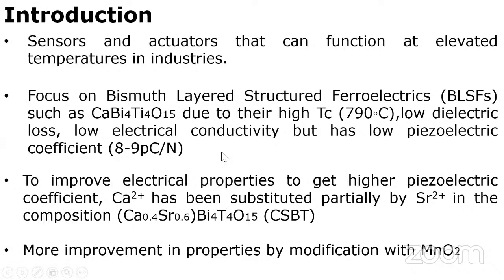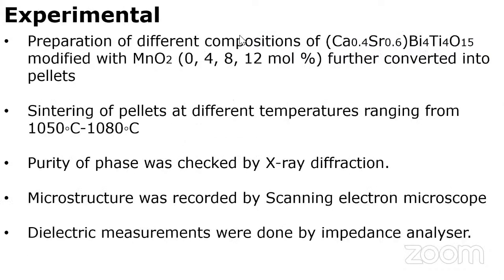low piezoelectric coefficient. So in order to further improve the piezoelectric properties and other electrical properties, and to get a higher piezoelectric coefficient, Ca2+ has been partially substituted by Sr2+ in the composition CSBT. For further improvement of the properties of CSBT, we have added MnO2 as an additive to the composition.